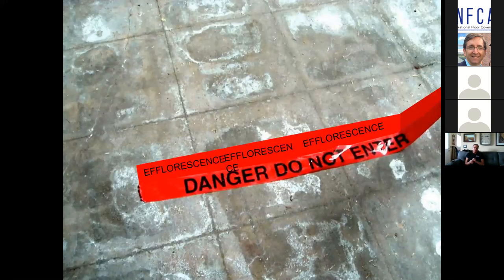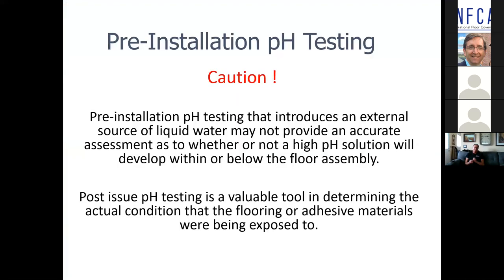And here you see some failed flooring that was removed, and you can see the salts, if you will, alkali salts underneath the surface. Pre-installation, as I warned you, we are actually, I believe, very close at ASTM to removing the requirement in ASTM F710. We're going to move a discussion of pre-installation pH testing to the appendices. They may ultimately develop a test procedure.